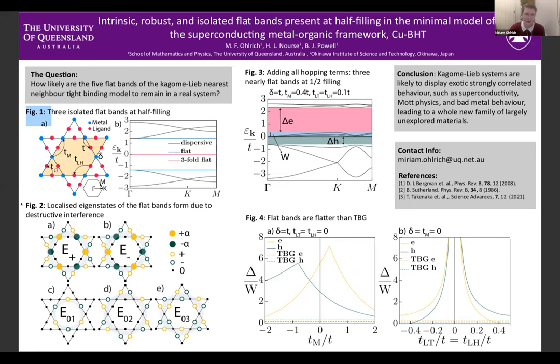So the flat bands arise from the topology of the lattice through the construction of localized eigenstates, which have the energy of the flat bands. These states form closed loops due to destructive interference. Now, this picture still holds even after adding the metallic on-site energy and the metal-metal hopping shown in figure one. However, when the ligand hoppings are added, you can't make this argument anymore, and you lose the exact flatness of the bands. However, when this happens, our bands at half filling are still flatter and more isolated than those of twisted bilayer graphene for a vast array of hopping strengths.